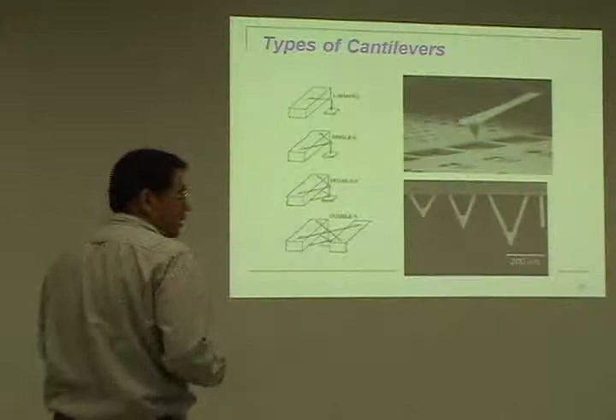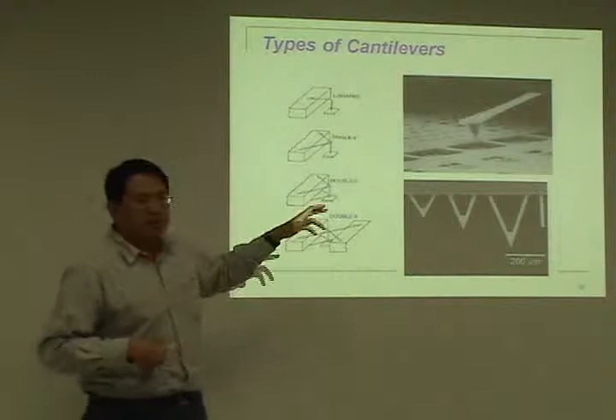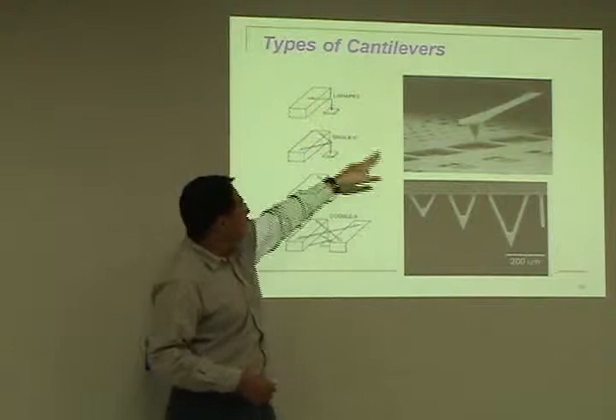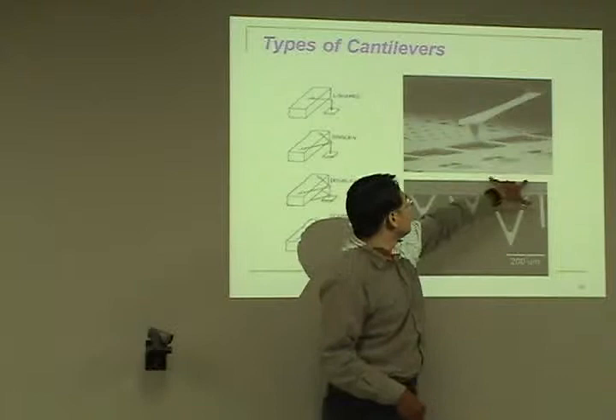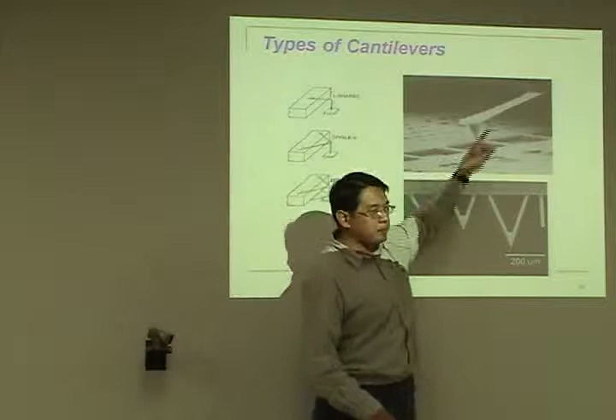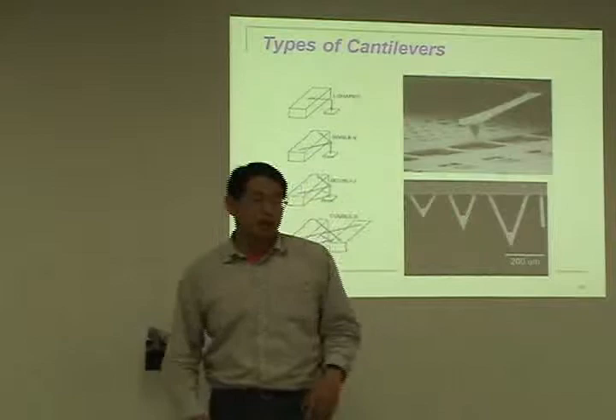The cantilever and tip are basically the probe of the surface, and their design is very important for achieving atomic resolution. There is an L-shaped cantilever visible here in the scanning electron microscopy image — it is a few hundred microns long. There is also a V-shaped cantilever. For contact mode, the cantilever is closer to the V shape, while for tapping mode, because you need strong oscillation, you use the L-shaped structure.